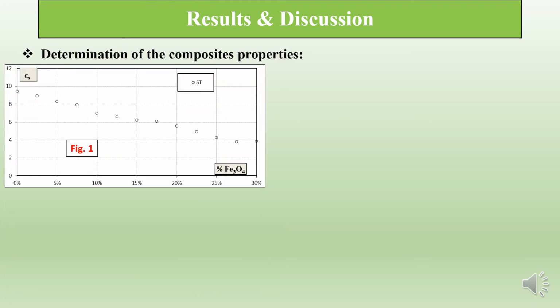Now, results and discussions. We propose through this section the determination of the composite's properties. First, figure 1 shows the static permittivity variation of composites at a constant frequency value of 200 MHz over all load volume fractions. The examination of the graphic results elucidates a visible decrease in the real permittivity of the composites when the iron oxide volume fraction goes up.